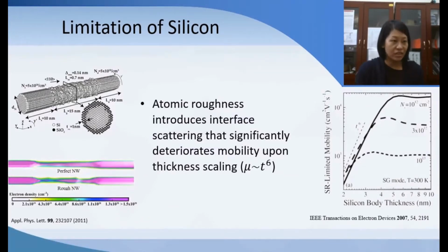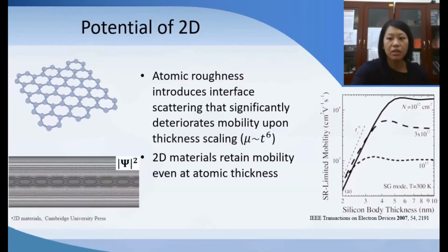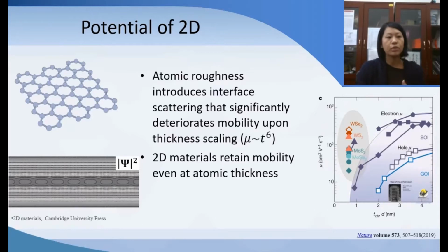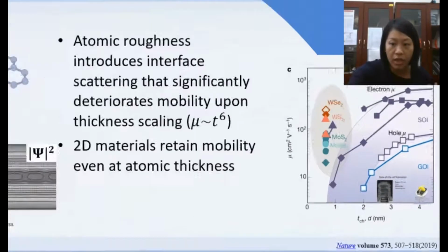For example, currently silicon itself is a 3D material, so the roughness by itself is too big that you cannot avoid the electron scattering effect. And so with the dimension getting smaller and smaller, the mobility is getting really tiny. Look at this trend: when the thickness is below 5 nanometer, the mobility is dropping exponentially. And when it reaches 2 nanometer, there's almost no mobility. That's why we start to introduce 2D materials, because they are atomically flat. People have demonstrated that at 1 nanometer thickness, the mobility of 2D material is much better than other current semiconductor thin materials.